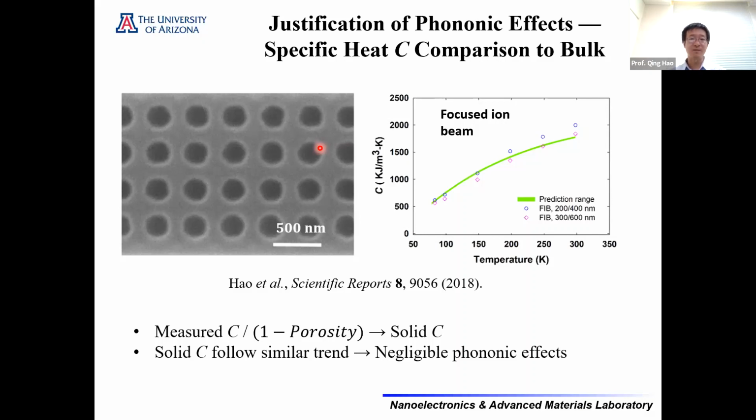So people can see some superlattice with a structure size of 5 nanometers. You can see some wave effects, and superlattices have atomic-level smooth interfaces, right? So that's why you can see it. But for those nanofabricated nanopores, usually the pore edge is rougher, right?